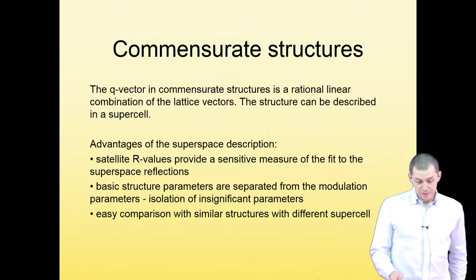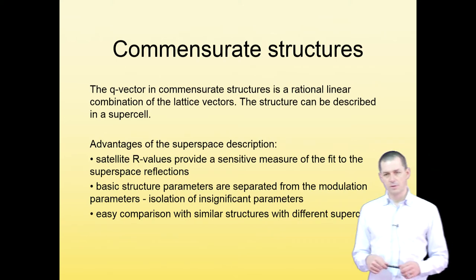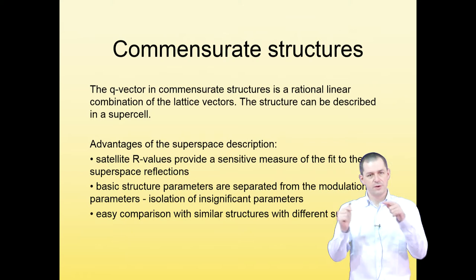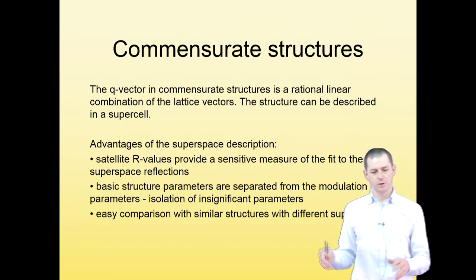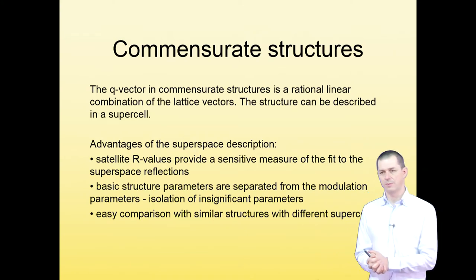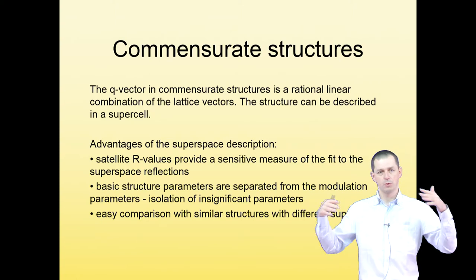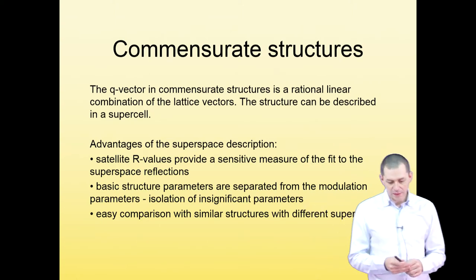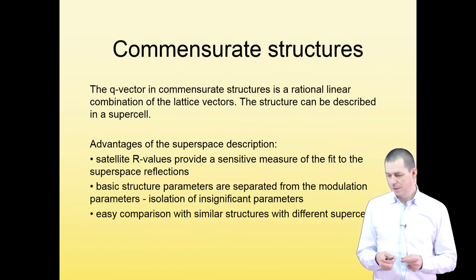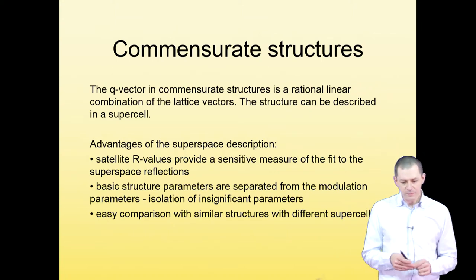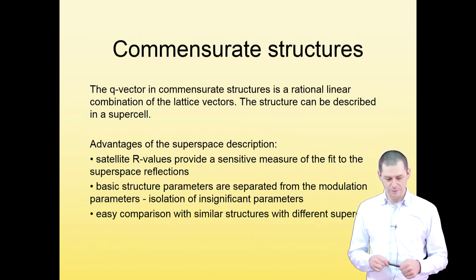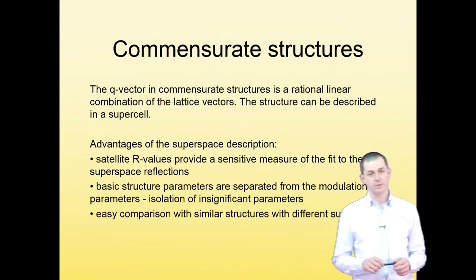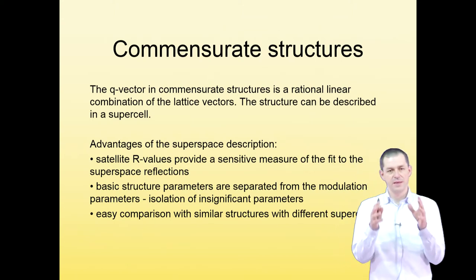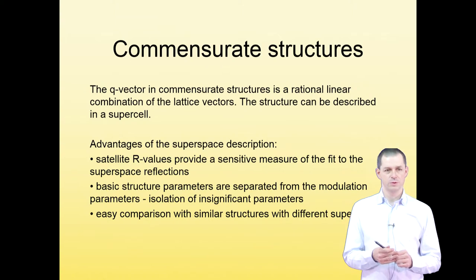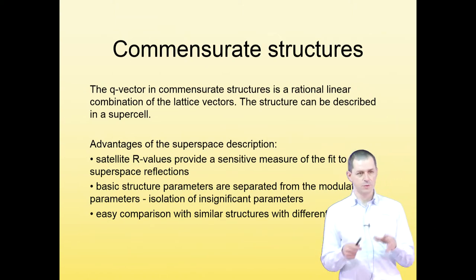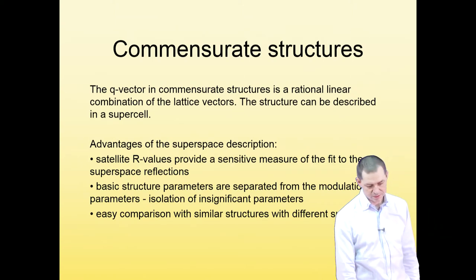What is more important is that the basic structure parameters are separated from the modulation parameters. So the atomic positions are separated from slight variations of the position from one unit cell to another. So you can isolate insignificant parameters. Maybe some atoms do not have modulation at all, so you do not need to modulate them. And you also limit correlations in the structure refinement. That's very important for stabilizing the refinement. And last but not least, if you have similar structures which have the same basic structure, same average structure, but different modulations, you can easily compare similar structures if you describe them in the same superspace model.